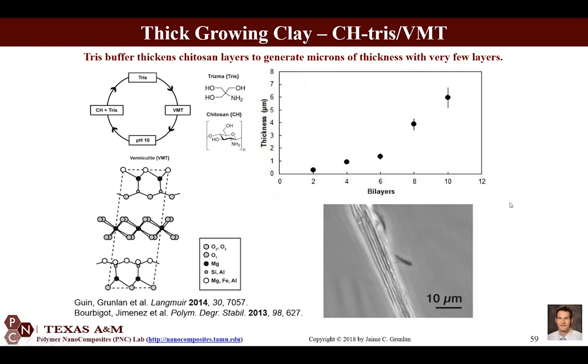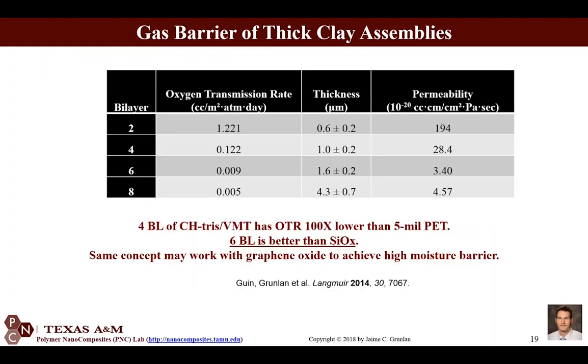And you can actually use an optical microscope to see this layer by layer assembly, which is a super, super thick layer by layer film. And so if I look at oxygen transmission rate, just a 4 bilayer film had 0.122 in these units, cubic centimeter per meter squared per day. The 5 mil PET substrate that we were using, that's almost 100 times improvement over the 5 mil PET, which is 125 microns thick. So you add 1 or 2 microns and you get 100 times improvement over 125 micron film. So 4 bilayers is 8 total layers.